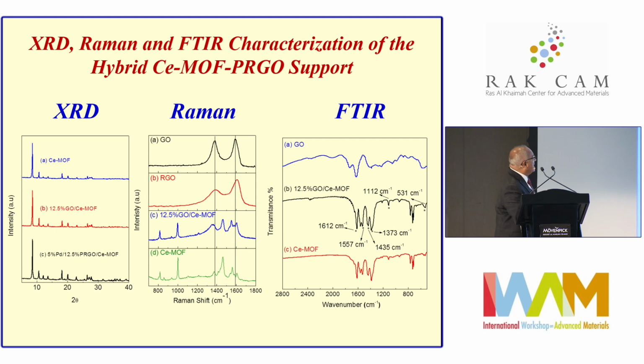I'm showing quickly that the XRD of the cerium-MOF and the hybrid structure are not changing. This you can see here. In this case, the middle pattern is 12.5%. This is the optimized ratio of graphene oxide in the hybrid structure. This is what we found to be the most active support, this 12.5%. After that, we cannot get better properties for the support.